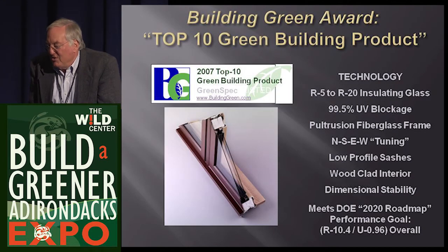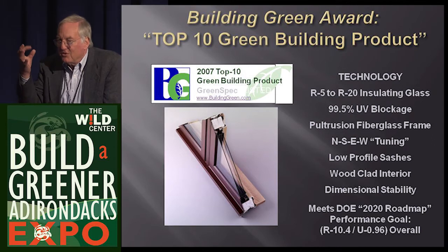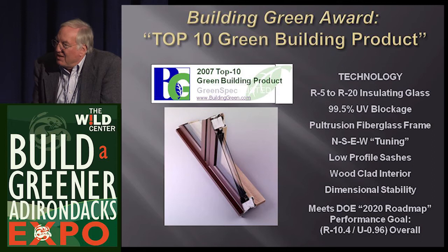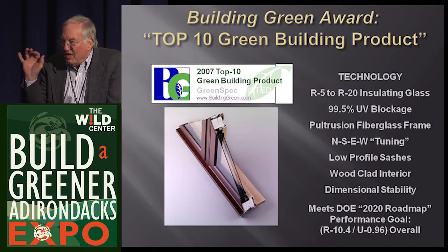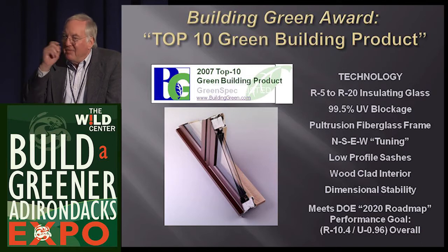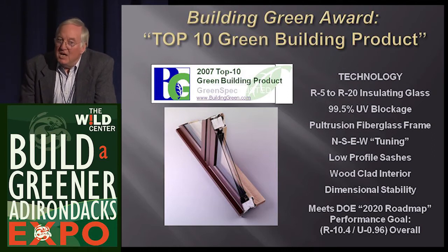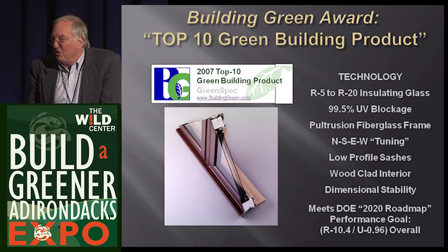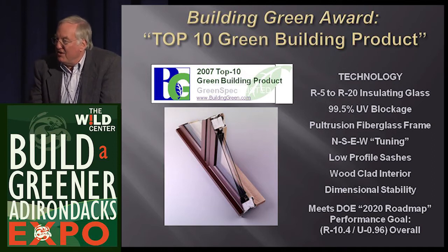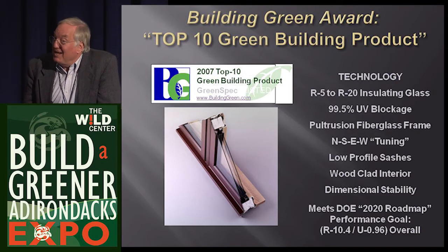The cross-section of windows is getting wider. Triple glass is becoming relatively standard - three panes of glass at R3 can jump to about R-8, because you have more surfaces to coat with low emissivity coatings and more air spaces to stop acoustic and thermal energy. A half inch of air between two panes is about optimal. If you make it wider, convection kicks in and R-value goes down.